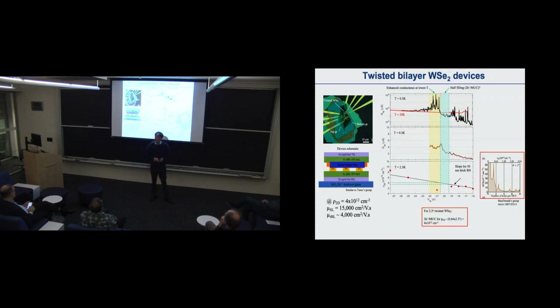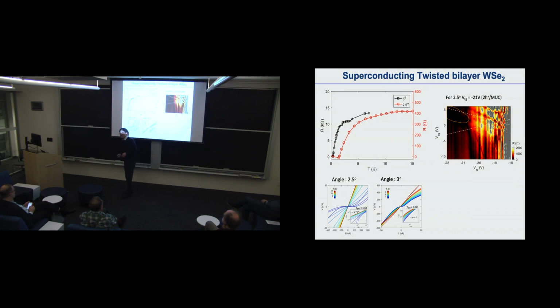Of course, this story goes on—you don't have to work on graphene. There are many other two-dimensional systems; you just stack these materials. For example, here with two semiconductors, tungsten diselenide—stack them together and you can create correlated insulator states. Not surprisingly, when you dope this, it also shows indications of superconductivity, although this data is less solid than before. But at least this tells you there's a fertile playground, using these 2D materials and their different stackings, to study strongly correlated systems. Thank you very much.